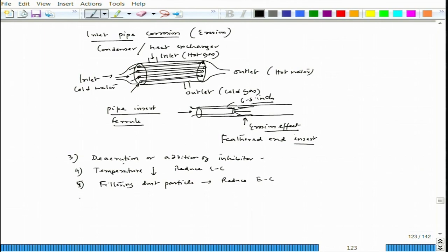Okay. People can think of hard coating. Adherent hard coating can reduce the erosion corrosion effect. Now seventh is, people can think of cathodic protection. It is not a very common practice to reduce erosion corrosion, but still people use a zinc plug in the case of a water pump. The zinc plug gives sacrificial protection to the pump material, fine. So these are some of the examples which can prevent or combat erosion corrosion.